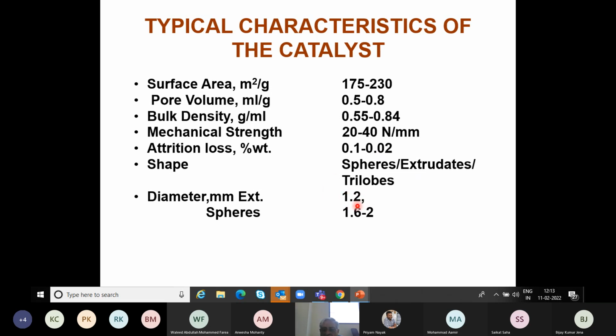But these extrudates are the shape which is preferred, either extrudate or trilobe. This is the shape which is preferred in semi-regenerative catalytic technology, that means the semi-regenerative reformers, while spheres are preferred in CCR. Why are spheres preferred in CCR? Because in the continuous catalytic reformers, the catalyst moves, so it is easy to move a sphere rather than an extrudate. And these spheres are again 1.6 to maximum 2 millimeter diameter.